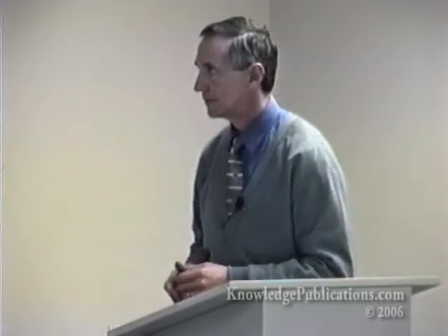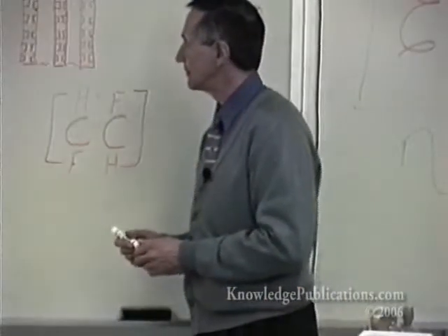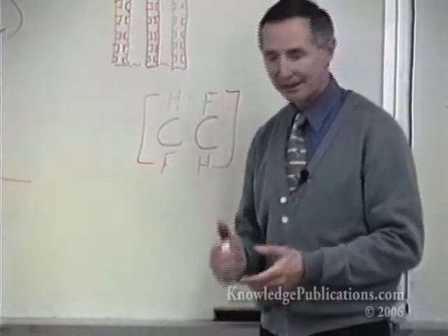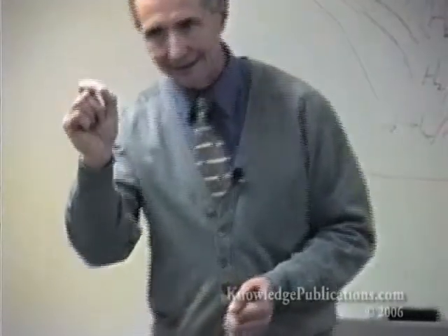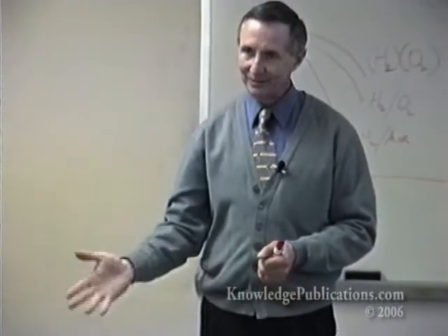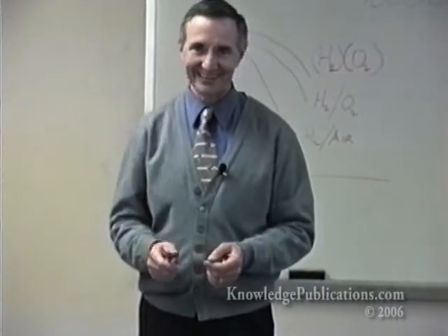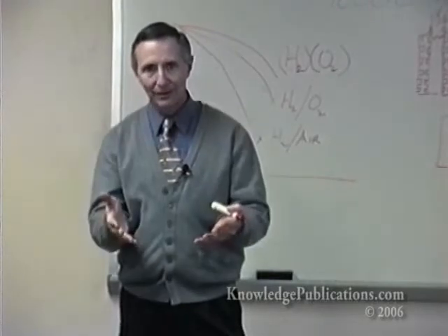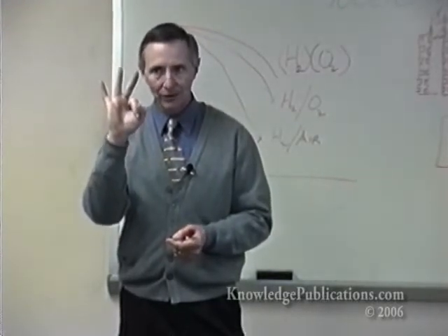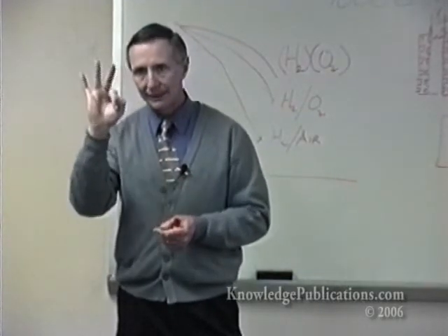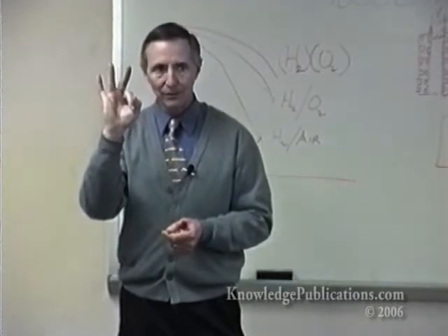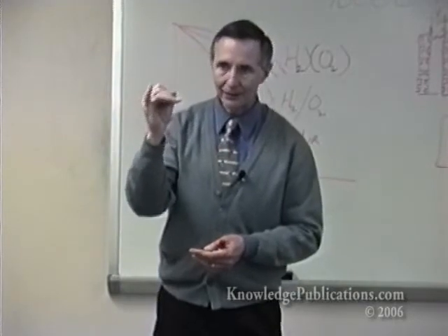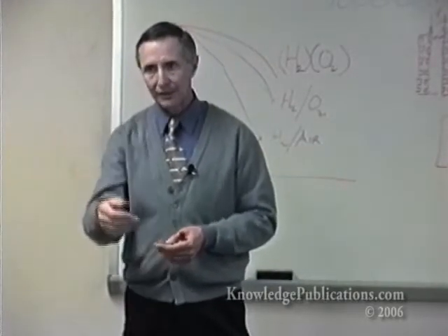Can you take this diagram that you've shown here and show how you would hold the catalyst? Well, the way you get the catalyst where you want it and not have much in inventory is this trick. There are several tricks. One is that you put the catalyst in ink, and you use either silk screen or laser printing techniques, it's the truth, to get a little bit, you're looking at dot type additions, a little bit where you hope you'll have this three-phase function. The three phases that you're trying to have come to common functionality are the gaseous hydrogen, that's one phase. The solid path for the electrons, another phase of the ensemble of stuff that you have available. And you have to have the ion go somewhere. So that's the liquid phosphoric acid or whatever.